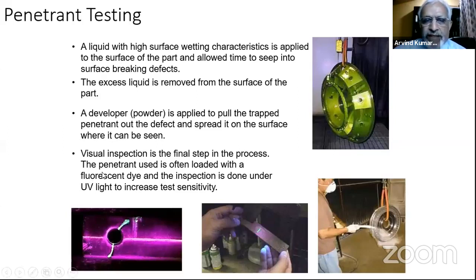And then that indication is called a visible solvent penetrant process. Whereas the other one is a fluorescent technique. What you see in this slide is a fluorescent technique where you have a penetrant which will have a fluorescence, which the indication, if it is seen under UV light, it will glow and it will fluoresce. This technique is generally applied on machined components and where the sensitivity requirements are high, where you are expecting tight fatigue cracks and such defects. There we go for a more sensitive method, which is a fluorescent dye penetrant testing.